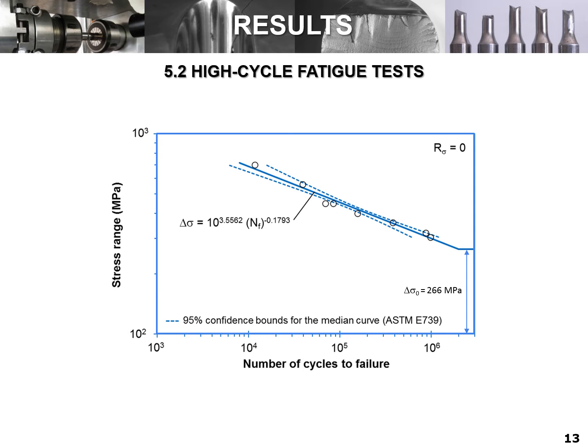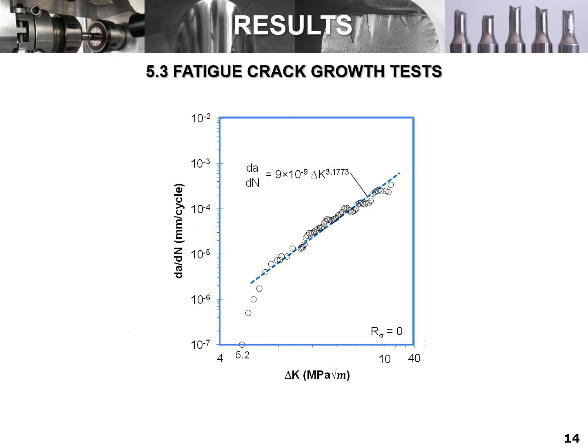Here, the fatigue limit stress was defined as the maximum value at which the specimen can endure 2 million cycles, and was equal to 266 megapascals. As far as the stress intensity factor range threshold is concerned, the results obtained from the fatigue crack growth measurements are shown in the figure.